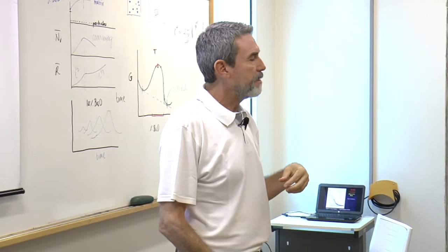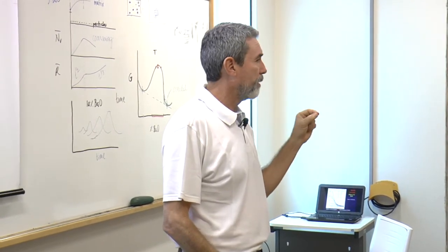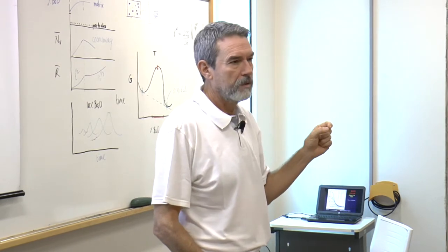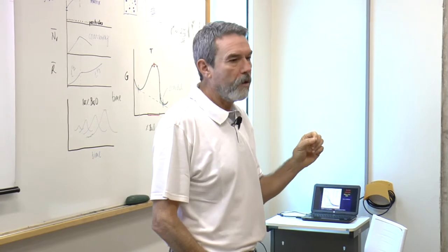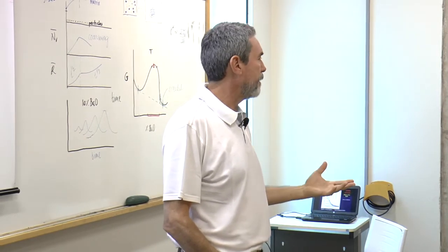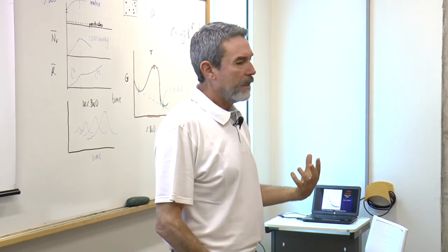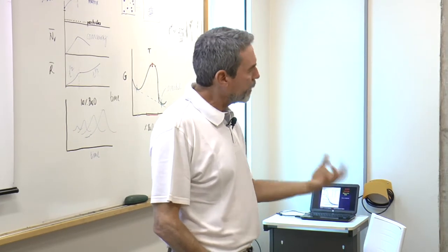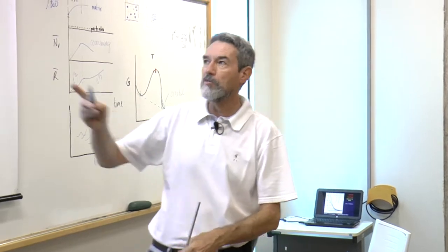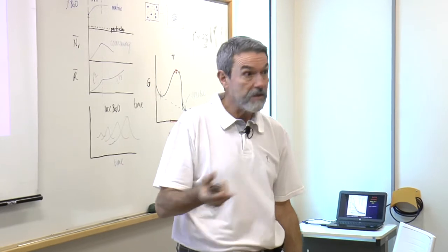Now, X-rays have wavelengths much smaller, 1, 2 angstrom. So if you have very small particles, they scatter X-rays. So small angle X-ray scattering is a way to measure the scattering of very small nano-sized particles by X-rays. You don't see the scattering of these particles by visible light.